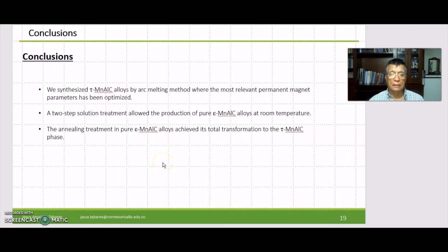Here I present the main conclusions of this work. We produce tau manganese aluminum carbon alloys by an arc melting method where the most relevant permanent magnet parameters have been optimized. A two-step solution treatment allowed to produce a pure epsilon manganese aluminum carbon alloy at room temperature, and the annealing treatment in the pure epsilon manganese aluminum carbon alloy achieved its total transformation to the tau manganese aluminum phase. This is the main conclusion in our work.